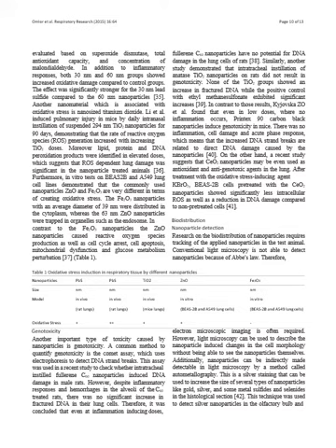The ferric oxide nanoparticles with an average diameter of 39 nanometer were distributed in the cytoplasm, whereas 63 nanometer zinc oxide nanoparticles were trapped in organelles such as endosomes. In contrast to the ferric oxide nanoparticles, the zinc oxide nanoparticles caused reactive oxygen species production as well as cell cycle arrest, cell apoptosis, mitochondrial dysfunction, and glucose metabolism perturbation.